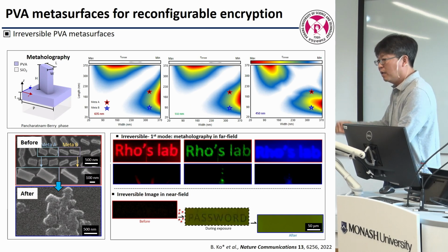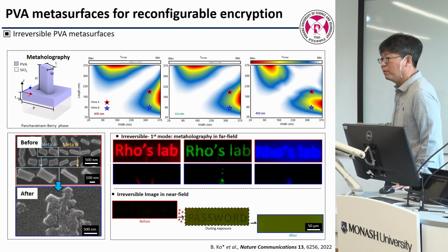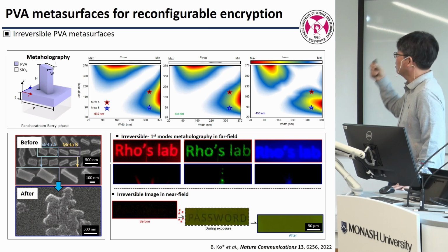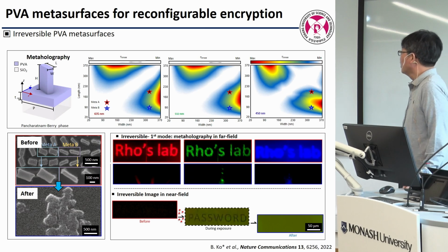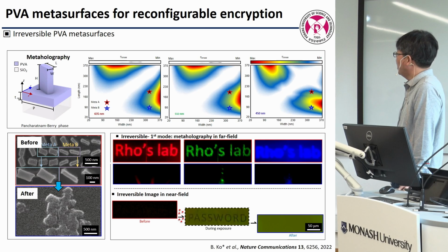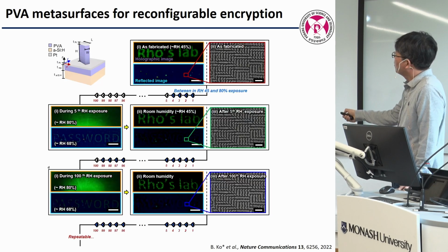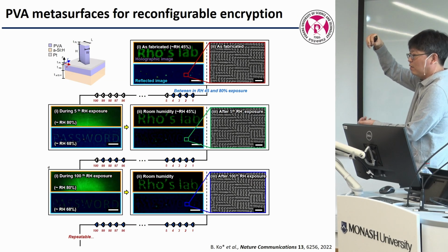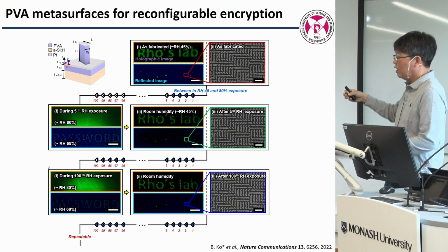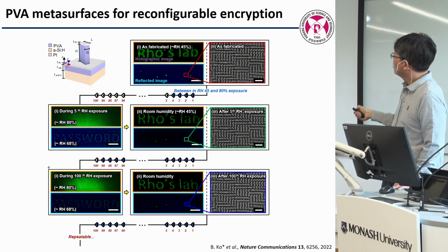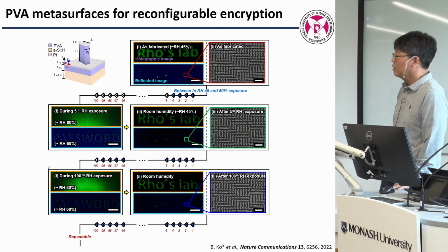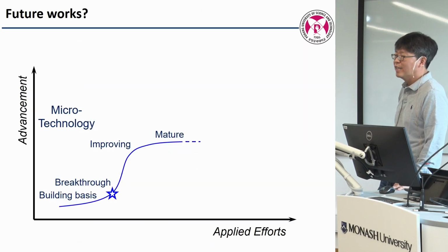And while they are broken, some amplitude, some structural color image suddenly appears. So this is your password, and then it's gone. So we claim this is a one-time password or one-time security sticker. So that's what we named this work, and we can do further. So at the bottom and top we sandwich with metal, and they don't collapse. They can swell, but they come back to the original shape. So hologram, no color; humidity in, hologram is gone, color comes out; humidity is removed, and the hologram comes back again. So this is a reconfigurable security tag, we claim, for humidity sensing.